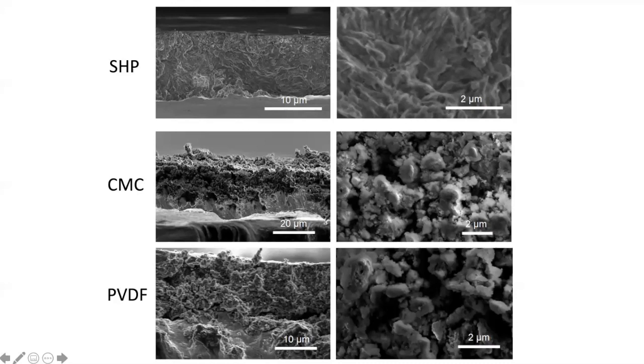But if you look at the cross section of these two other types of materials people typically use, they were useful for nanoparticles, can stabilize nanoparticles, but not microparticles. So CMC is a type of cellulose material. PVDF is the other one I mentioned. And you can see here a lot of porous structure. That's due to the fracture of the material. And eventually the battery stopped working because, within the porous structure, the particles lose contact with each other. And then it's no longer electrically conductive to allow lithium to be able to deposit.